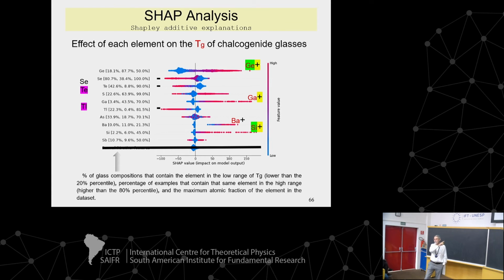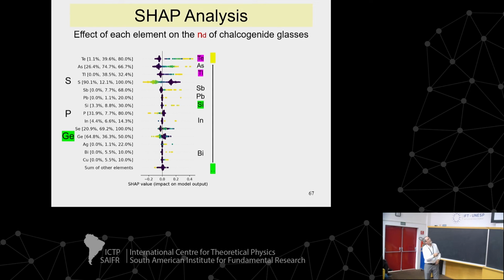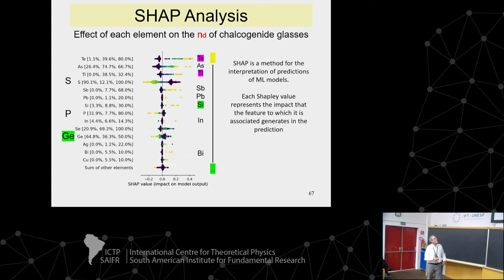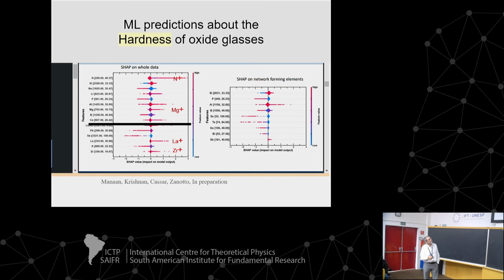I never worked with chalcogenide glasses, but now I can do chalcogenide glasses with much less effort. I am not showing the result here, but these elements in yellow, this, this, and this, also decrease the CTE. So if I want a glass with low coefficient of thermal expansion and high TG, I can use germanium, gallium, or silicon. So combinations of properties. Or I want a glass with a high refractive index. Oh, okay, then you go for tellurium, thallium, antimony, lead, silicon, indium, or bismuth. See the game. This is a real result of machine learning. And I can also do the same thing for hardness, but I'm running out of time.